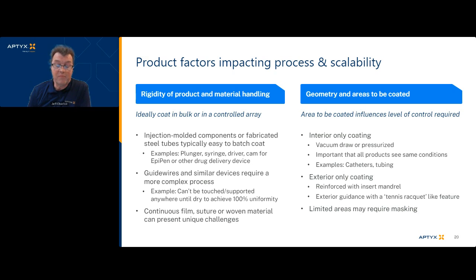And we'll do that by putting mandrels or putting some type of masking on. If we have to draw the coating into the interior of the product, it's not uncommon to use vacuum to do so. Based on the properties of the coating, the vacuum and the amount of vacuum applied and the duration which it'll take to draw that up to a precise level can vary quite widely. To expel that coating, it's not uncommon to use an inert gas or some type of pressurized supply to then move or purge that coating from the interior of the tube or the lumen that's being coated, and then to assure that it is maybe purged for a period of time, not only acting as a method to make sure it doesn't clog, but also somewhat of a drying step to assure that the coating is set up in the interior and is properly deposited over that period.